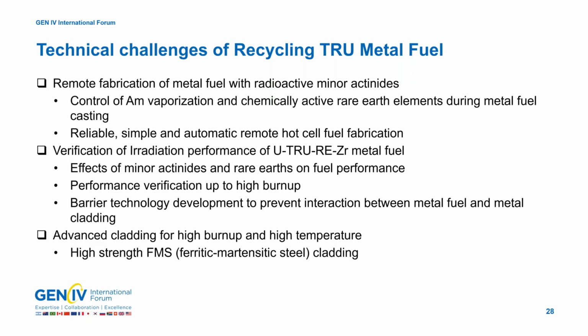And also the rare earth element impurities are very chemically active. So those need to be taken care of for pin fabrication. So those are challenging for fabrication, and also the irradiation performance of these TRU fuels with some rare earth impurities and also minor actinides needs to be checked, and because of the rare earths, barrier technology is more helpful here for TRU fuels to prevent interaction. So those are about the irradiation performance side of the TRU fuel.